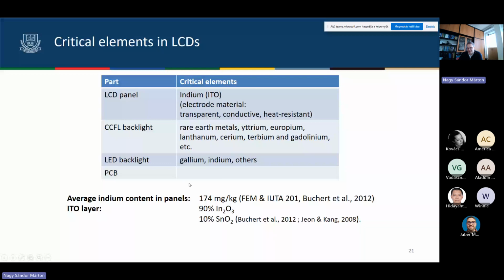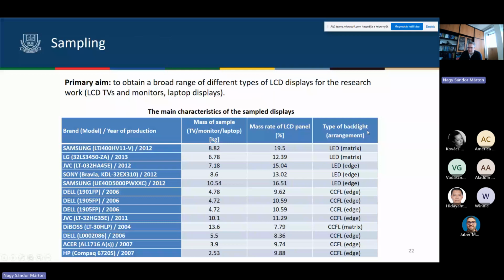The indium content we measured is a little bit less than 174 milligram per kilogram in the display panels, not in the TVs, not in the equipment, only in the display panels. It's a quite low amount of indium. During our experiments, we collected a quite large sample. You can see here we recorded the producer and the type of this equipment, and we realized that the LCD panel itself is maybe 7 to 15% by mass of the whole equipment.